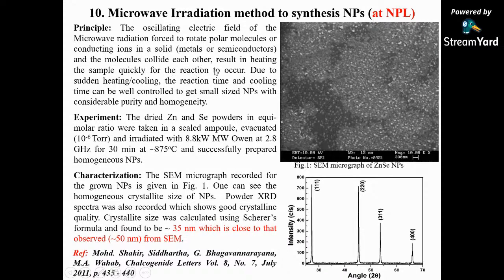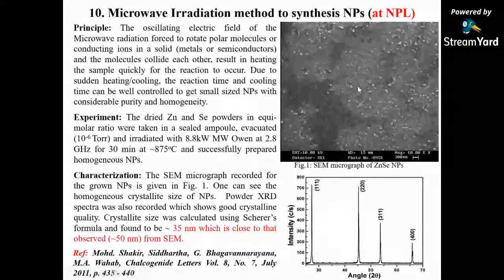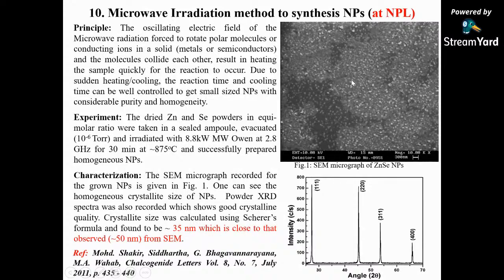How are the microwaves heating? The semiconductors are ionic materials. They have ions, and they will try to vibrate with the oscillating electric field, and friction is created in the collisions, and thereby heating comes. Because of that sudden high heating uniformly at each place, they are subjected to the chemical reaction. ZnSe will be formed, and you can get very uniform, beautiful nanoparticles with a very simple technique. We have succeeded in making these ZnSe nanoparticles, and we have characterized them by powder XRD and SEM also.